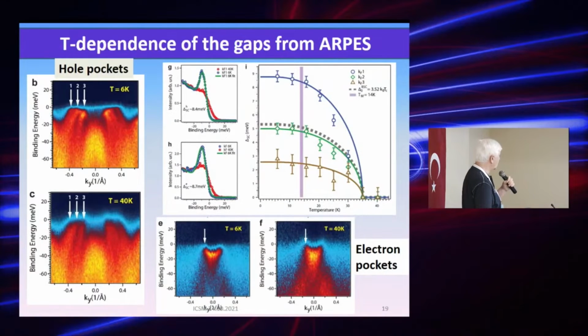Now, since these are momentum resolved measurements, we identify with no discussion which gap belongs to which Fermi surface sheets. In these measurements, we identified three gaps. The largest gap actually belongs to the two pockets. One of them is a hole and another one is an electron, and the error bars are insufficient to resolve the two of them. So they evolve versus temperature in a rather usual fashion.